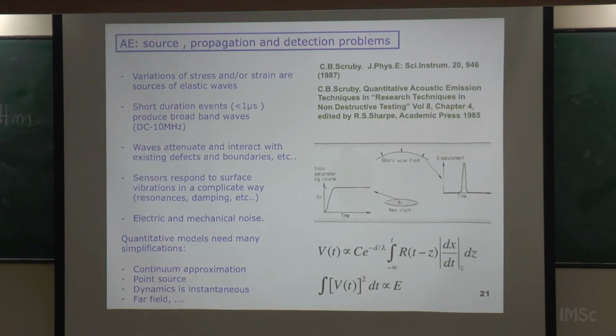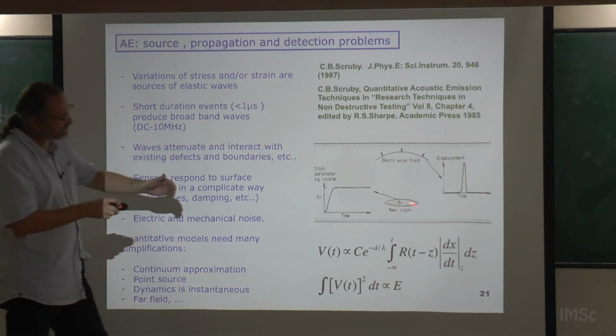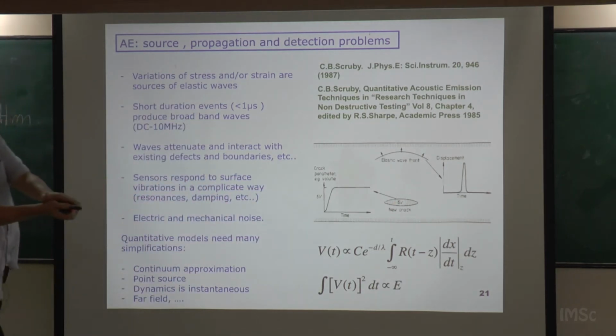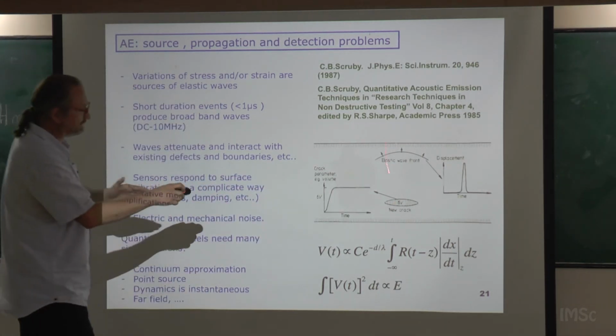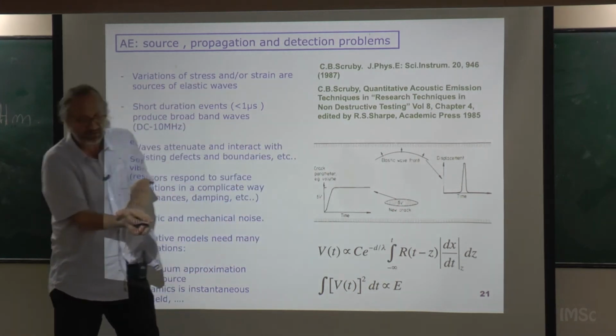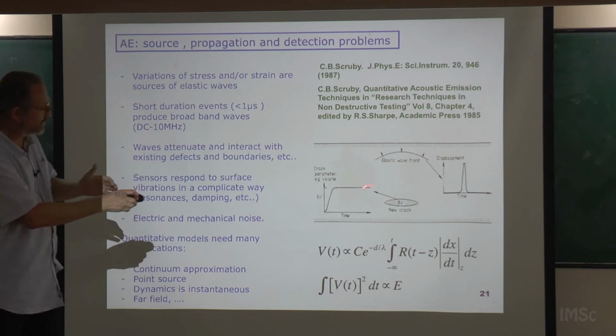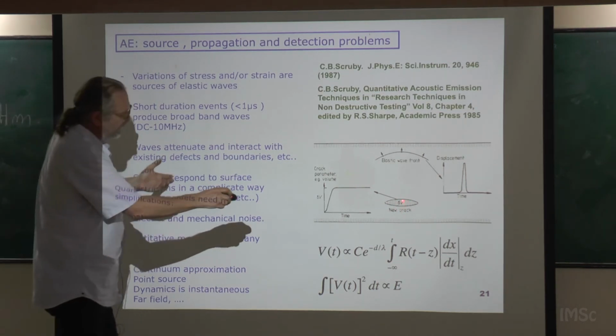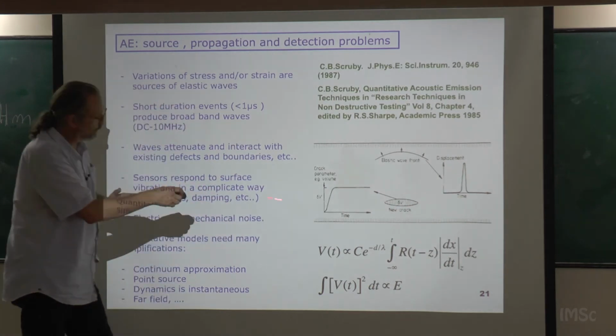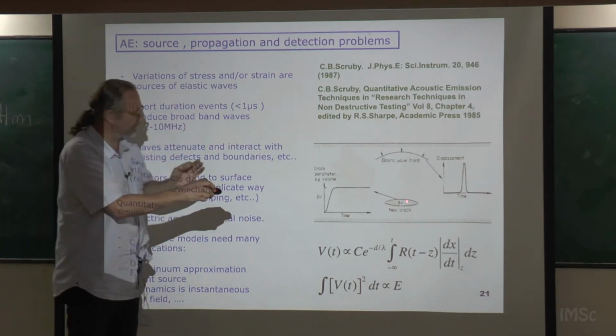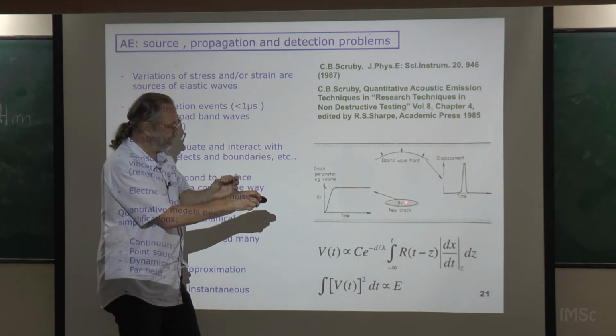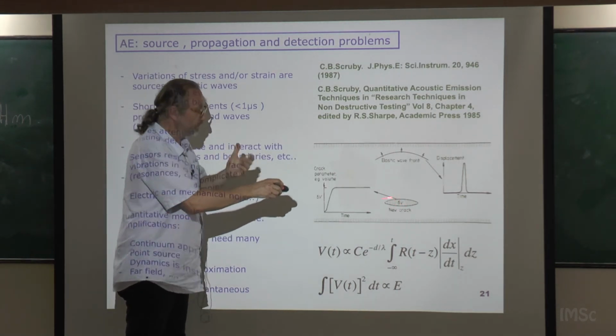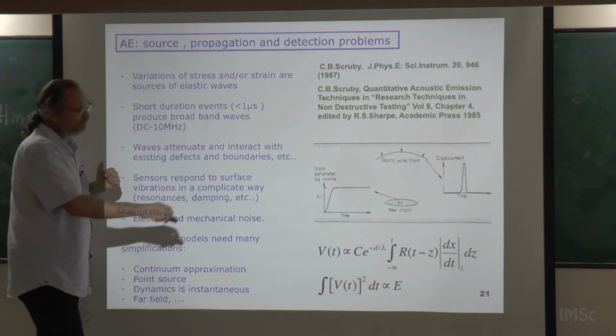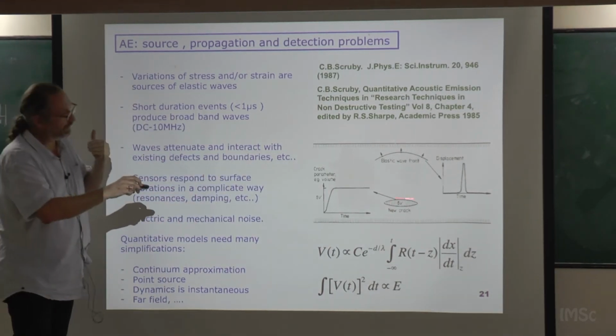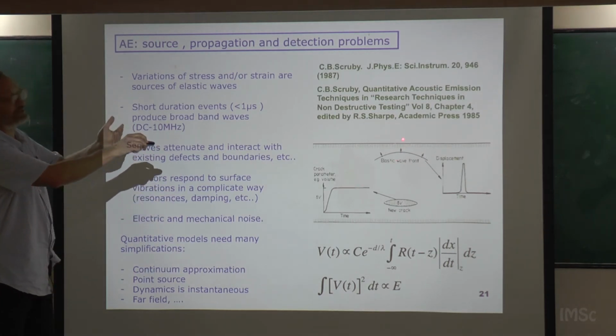Okay, so what is acoustic emission? Essentially, when in a solid you have an interface, or in this case a lens-shaped region, that suddenly becomes bigger, so there is a phase that grows, could be the martensitic phase growing. You plot here, for instance, the volume as a function of time. You have a step, a jump, so this phase decides to grow, and the phase transition advances, so this volume has to increase. You have a fast jump. This fast jump generates an elastic wave that propagates and reaches the surface of the system.